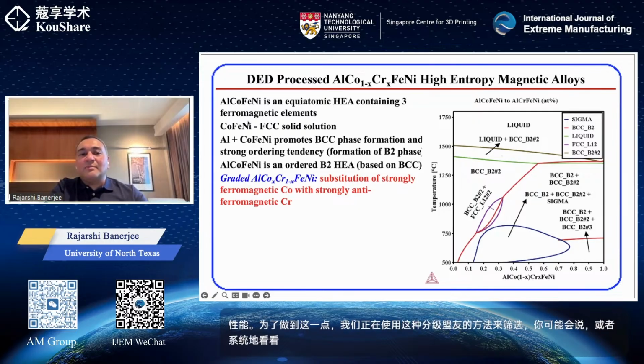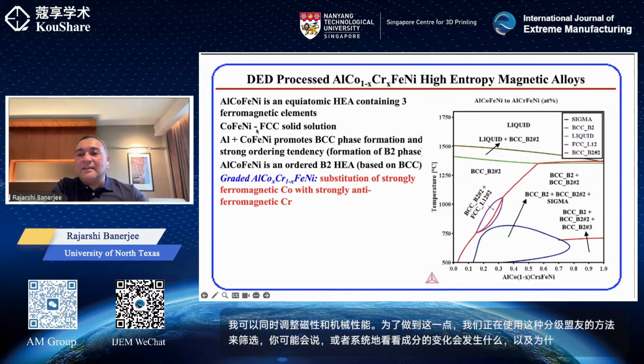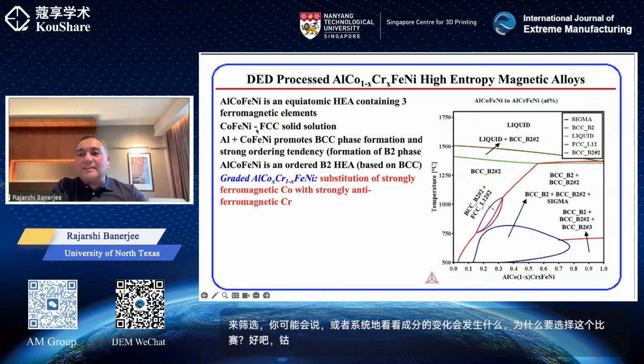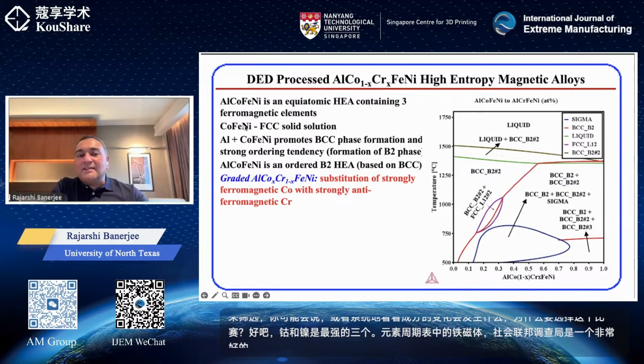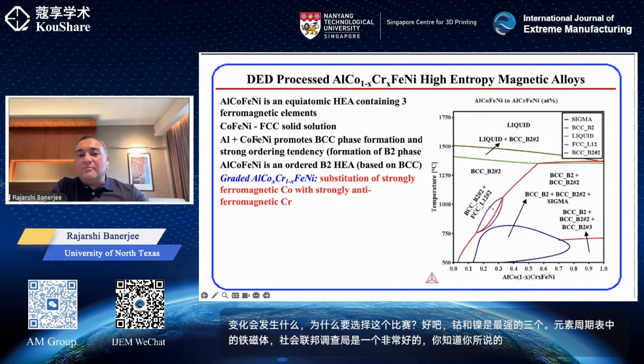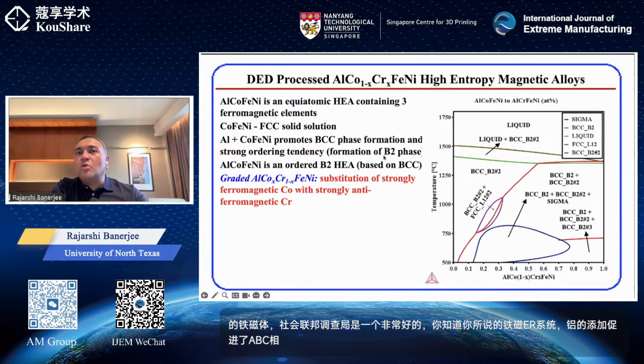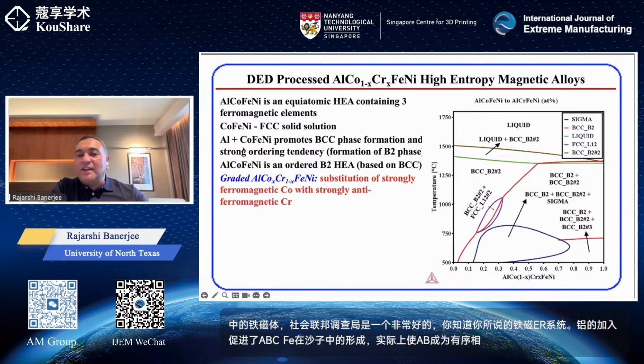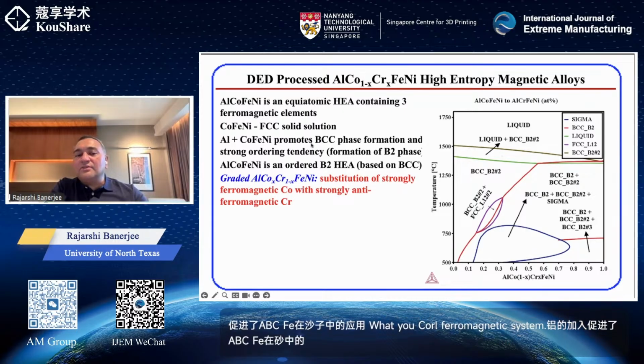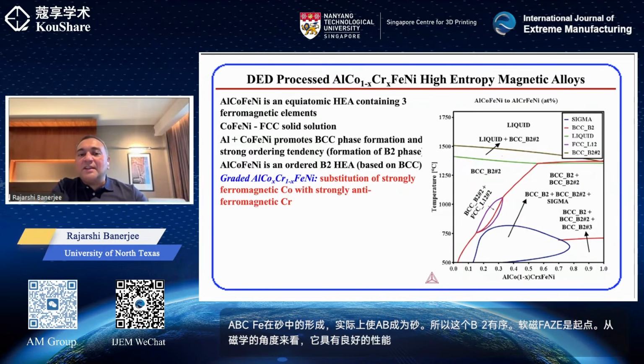Now, why select this composition? Well, cobalt, iron, and nickel are three of the strongest ferromagnets in the periodic table. So CoFeNi is a very good ferromagnetic system. Addition of aluminum promotes a BCC phase formation and actually makes a B2 ordered phase. So this B2 ordered soft magnetic phase is the starting point. It has good properties from a magnetism point of view. However, we are trying to see if we can tailor the magnetic properties and the mechanical properties by adding chromium.